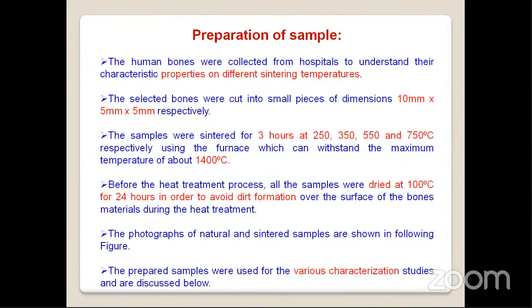The furnace I have used in our laboratory can withstand a maximum temperature of about 1400 degrees centigrade. Before the heat treatment process, we need to sinter or dry the sample at 100 degrees centigrade for at least 20 to 24 hours to remove the dirt over the surface of the bones. We want a clear pure bone, so we need to heat treat at 100 degrees centigrade for at least 20 to 24 hours. Okay, then I can show you the photograph. After that, we utilized all these materials for different characterizations in order to understand their physicochemical properties.